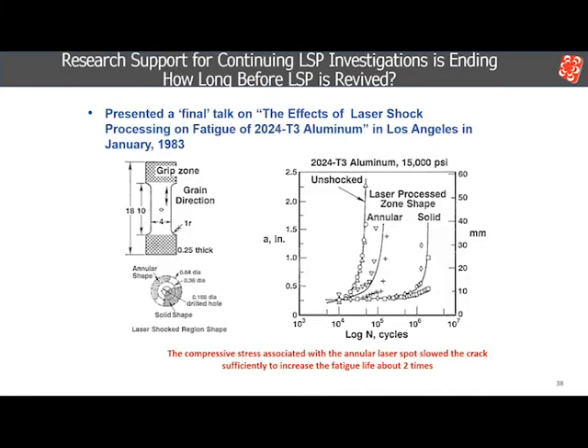This slide shows the application of an annular laser-shocked ring around a hole. The Air Force had commented that they did not want cracks they couldn't see. When the laser peen surface surrounded the hole, a crack would form on the hole surface at mid-thickness, tunnel under the surface, and not appear on the surface until it was almost at the edge of the laser peen spot. By laser peening an annular ring some distance from the edge of the hole, the crack was immediately visible, but it was slowed when it hit the compressive stress under the laser peened ring. This still provided a factor of 2 to 3 increase in the fatigue life.